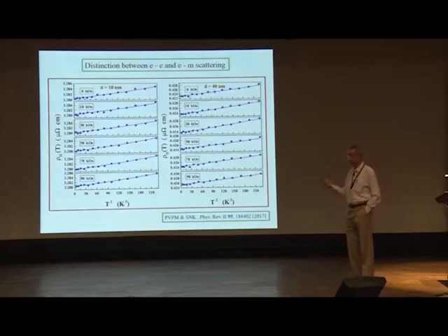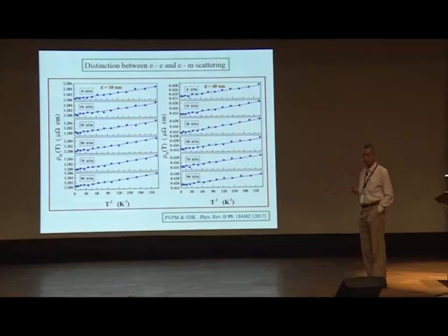So you have fewer magnons at high fields to scatter electrons. Okay? That means the electron-magnon scattering will get suppressed quickly when you apply the magnetic field, whereas electron-electron scattering would not get affected at all. So what you see here is that the coefficient of the T-square term is nothing but the slope of these curves, and you find that the slope does not change with field. So it's a clear indication that up to about 10 Kelvin or so, it is just the electron-electron scattering that is dominant.